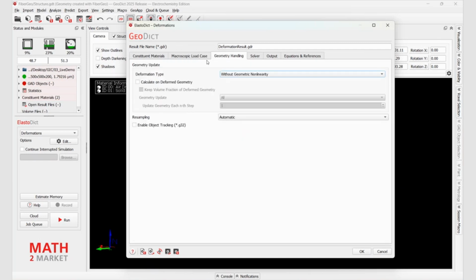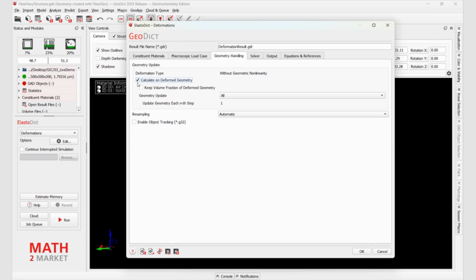Now important also is that in the geometry handling, I select calculate on deformed geometry. What does this mean? Well, if I do a 3% compression step, then fibers will touch each other that haven't touched each other before the compression. So I get new contact points, and this will increase the stiffness of the material, but only if I take into account in the next step that the geometry has actually been deformed and I get new contacts. So if I select this, I take this into account, because otherwise I will just have a linear stress strain curve, because it's a linear model. If I'm not calculating on the deformed geometry, I will always calculate the compression step from the original geometry, and I just get a linear output. But if I select this, after this 3% compression, the structure will be resampled.